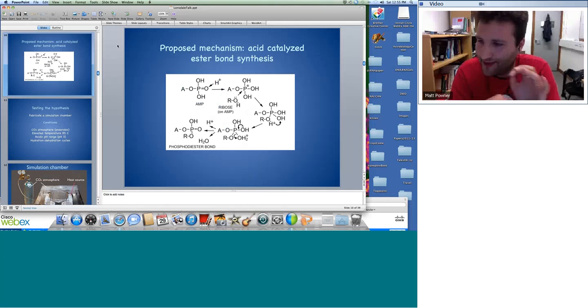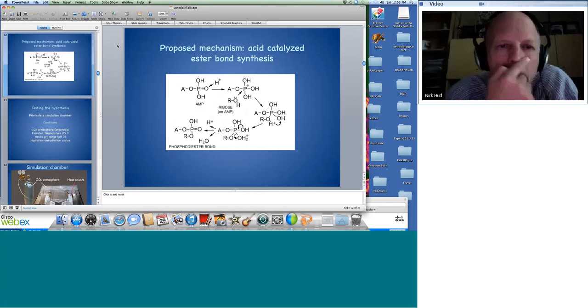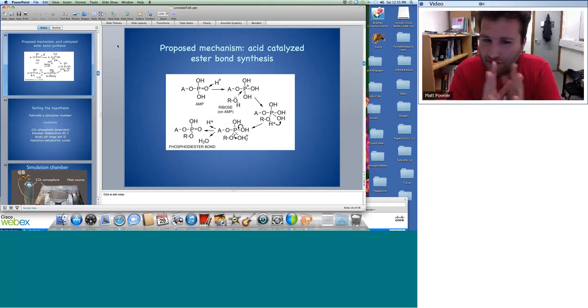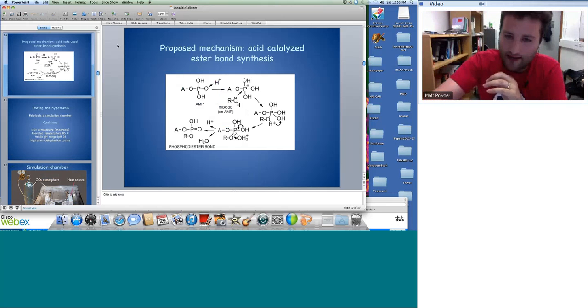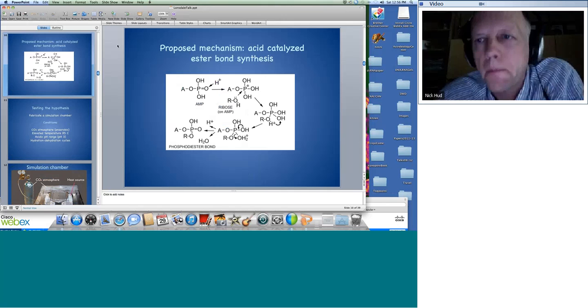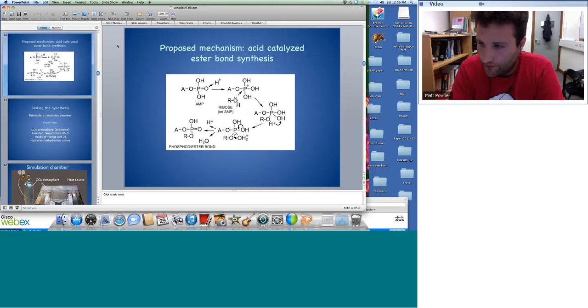Let me clarify. So you're suggesting that the actual ammonia adds to the phosphate? I'm wondering if it does. Potentially diamide phosphates maybe, but I wouldn't expect so at this pH. Nitrogen adding to phosphorus has a low affinity relative to oxygen and phosphorus. My guess is that the ammonia allows you to generate the species that's on our screen, top right. So you can lose a proton to phosphate. Absolutely, that's the first acid catalyst. And then as you lose the ammonia, for example by volatilization, you have a localized, very low pH, which allows you to access a different manifold of phosphate chemistry.